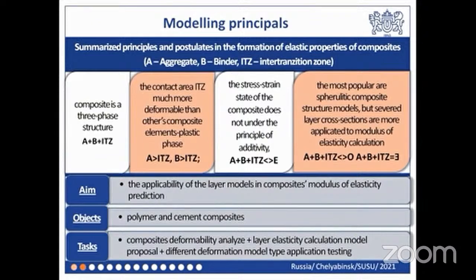Summarizing past and current research, the following principles in the formation of elastic properties of composites can be highlighted. First, a composite is a three-phase structure, basic elements of which are binding matrix, aggregate, and the contact area between them, or interfacial transition zone, ITZ. These components have different elasticity, and their different elasticity determines the overall deformation properties of the composite.